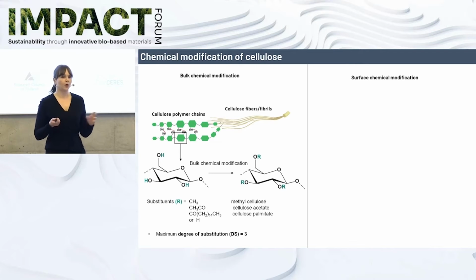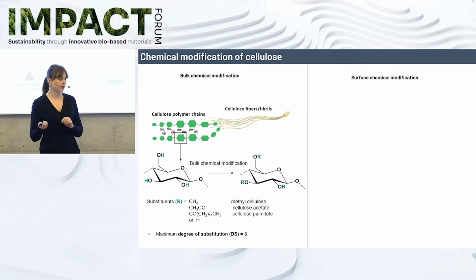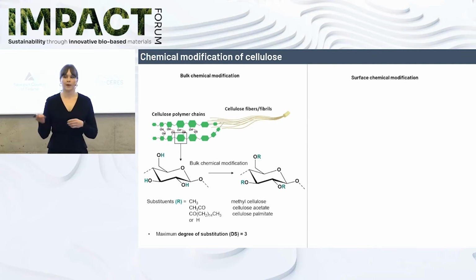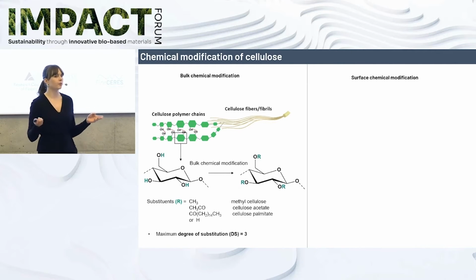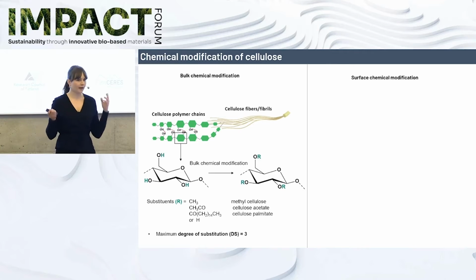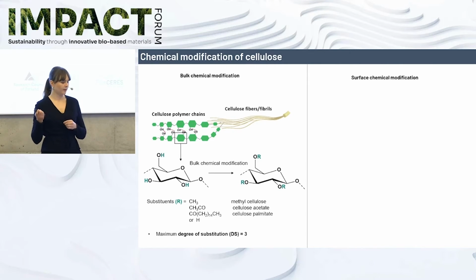But basically on the polymeric level, cellulose is composed of these sugar units, and each of the sugar units has 3 hydroxyl groups which can be then replaced by these different substituents. So these are all cellulose derivatives you might be very familiar with, for example, methyl cellulose or cellulose acetate, which is used, for example, in cigarette filters, and eyeglass frames usually are also made of cellulose acetate. And then the degree of modification is generally defined as the degree of substitution. So it ranges between 0 and 3, depending on how many of these hydroxyl groups are changed. So the maximum is 3.